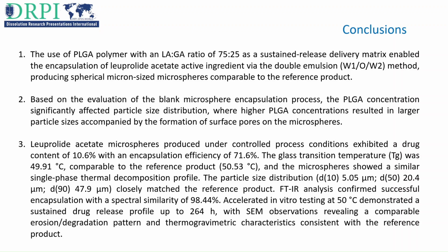Accelerated in vitro testing at 50 degrees Celsius demonstrated a sustained drug release profile up to 264 hours, with observations revealing a comparable erosion or degradation pattern and thermogravimetric characteristics consistent with the reference product. Our findings highlight the promise of PLGA microspheres for long-acting leuprolide delivery, paving the way for future in vivo and clinical investigations.